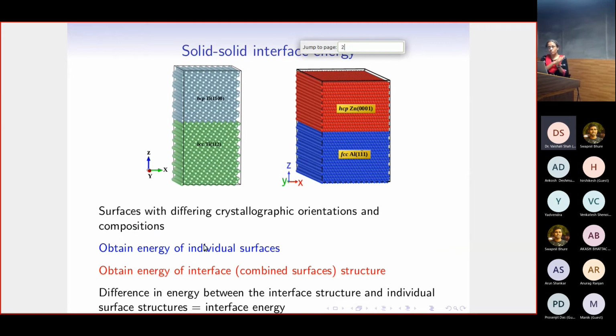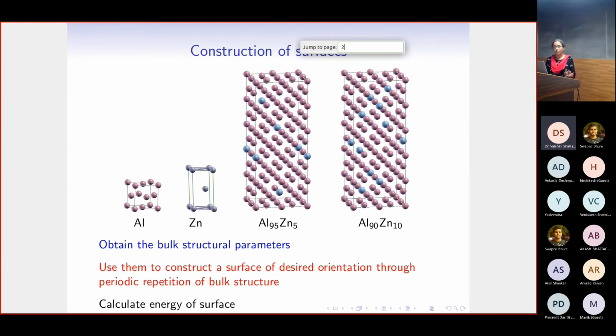And then I put these two surfaces together and again do the same calculation and obtain the energy for the combined structure. The difference in energy between the combined structure and the individual surface structures should give me the interface energy. So it looked like there was a nice simple way to do this. However, when we started to do this in practice, we realized there are difficulties. So let me take you through how we have gone through this process.